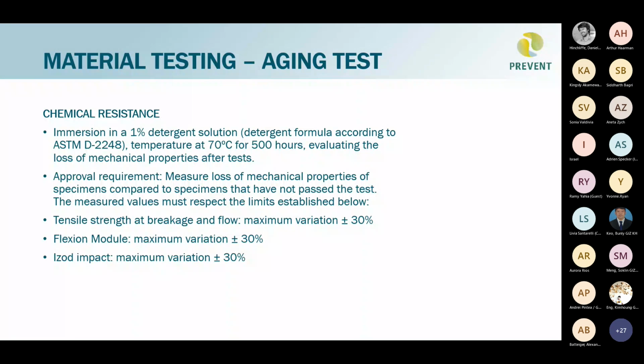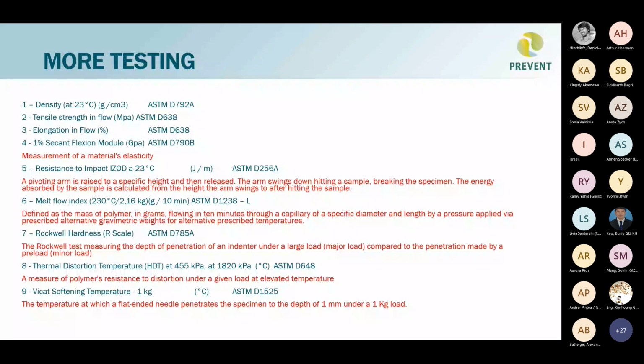And more tests that can be done: density, tensile strength, elongation and flow. Secant flexion modulus. This is the measurement of material elasticity. The Izod impact, we saw it on another page. They put a pivoting arm raised in the air at a specific height, and then it's released on the plastic sample, and the arm will swing down, hit the sample, and break the specimen. And the energy absorbed by the sample is calculated from the height the arm swings back up in the air. So this is the way they do it.